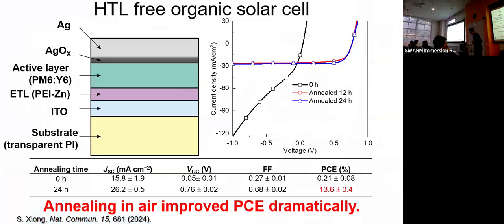Then the main finding, the important technical achievement, is to change the hole transport layer from the water-sensitive normal materials to water-insensitive ones. More specifically, we use thermally grown silver oxide layers as HTL materials, and we deposited the silver directly onto the active layer surface because there is no HTL, hole transport layer. The initial as-grown device shows very poor performance. As shown here, this black curve, the PCE is just 0.2 something, almost no solar cell performance.